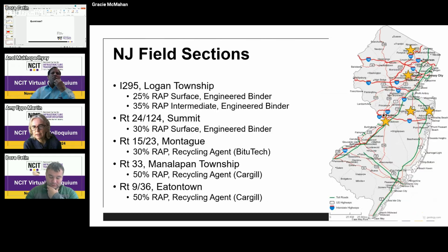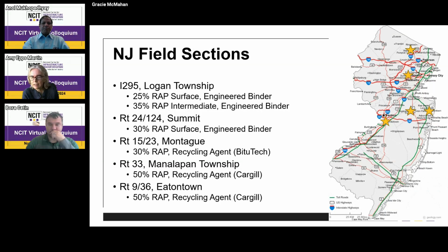Next slide, please. So just to step through a little bit, they have 5 field sections that are a number of years old now, and you'll see that in the next few slides, that are across the state of New Jersey. You can see there with the gold stars. And they have relatively high RAP contents, all the way from 25 at the surface to 50%. Some of them have recycling agents, some of them don't, as a way to mitigate that stiff, brittle material.